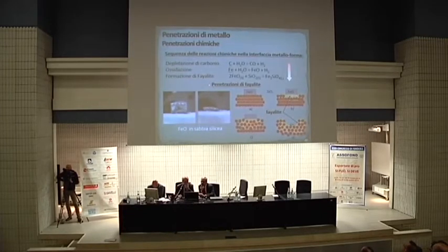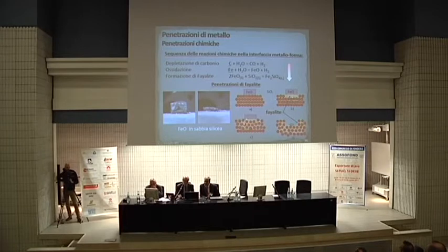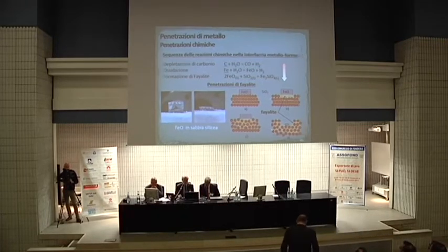I want to talk a little bit about chemical penetration. Here what happens, as we discussed, is that you have carbon that is oxidized by water vapors in the mold, and iron that is oxidized in the formation of fayalite. Here is a simple example. This time the substrate is sand, and this is an iron oxide. We start melting it, and what we see is it simply disappearing. It sinks into the sand. You have fayalite here, and the fayalite goes in, and at the end, this is what's left. So that's an example of how this penetration works.